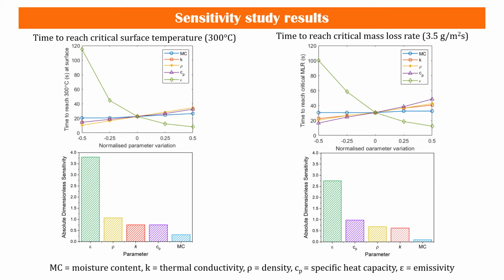As for the time to reach the critical mass loss rate, the figures on the right show that it is most sensitive to the emissivity, followed by the specific heat capacity and density. Similar results for both criteria are because the two ignition criteria are linked. The rate of the release of volatiles, which is the mass loss rate, is dependent on the rate of pyrolysis, which is dependent on the temperature of the sample.